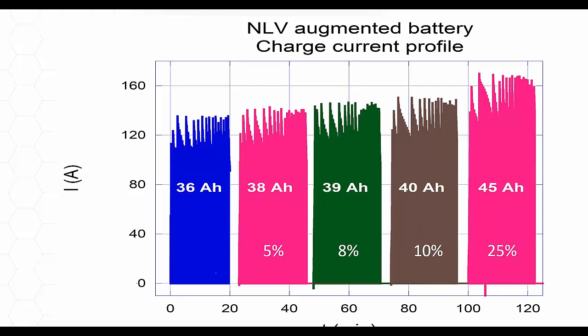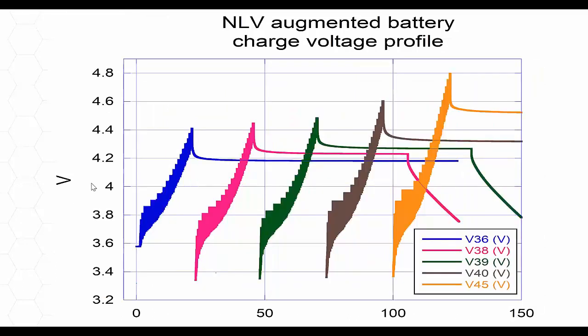And so we augmented the battery from Samsung by 20%, from 3,000 to 3,600. And the battery didn't heat up, and the battery is not affected much. The cycle capacity of the battery was not affected by the fact that we have extracted 20% more energy from the cell. So this is just to show you the voltage profile.